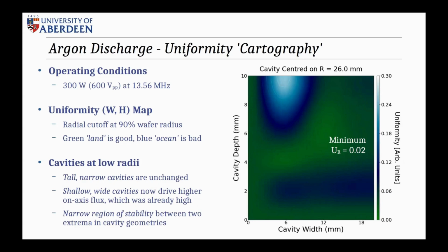No, we don't. Because if you move the cavity to a different location, just one cavity, one simple gas, and one wafer, you end up with what used to be your island of stability is now a lake of sadness, and you will drown. So what instead happens here, if you move the cavity towards the center, you have to navigate this little archipelago of stability, and you still get pretty good minimum uniformities, around 2%. So still good enough, but a totally different design.